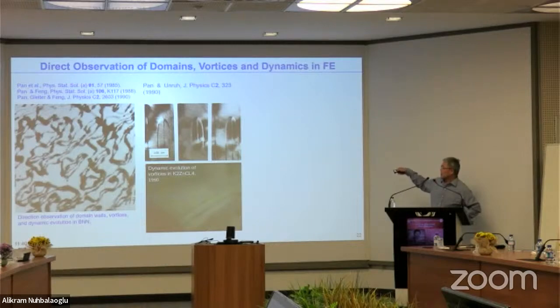And then you can see that there are two domain walls which are very close to each other, forming a pair. And then these three pairs can join together to form vortices. These vortices will change their configuration when you change the temperature. Change the temperature, you have a temperature gradient. Temperature gradient is the driving force that pushes the middle wall, and the vortices move.